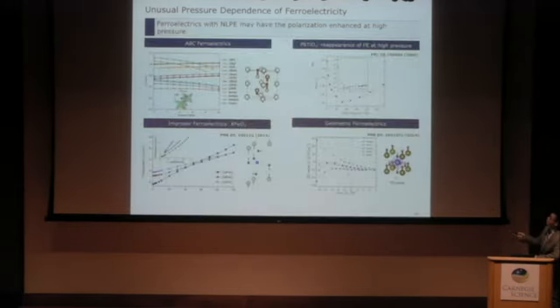I also would like to put our work in a bigger context. In the literature, people talk about pressure-enhanced ferroelectricity from time to time. I believe a lot of you are familiar with this work. In this paper, it was claimed that the ferroelectricity will reappear above some critical pressure. Maybe Ron has some new update, but it's clear that when we apply hydrostatic pressure, the polarization will become smaller. In this paper, they show that for some improper ferroelectrics, rare-earth ferrites, the polarization will also increase with increasing hydrostatic pressure. But in this case, it is because of a zone boundary mode.